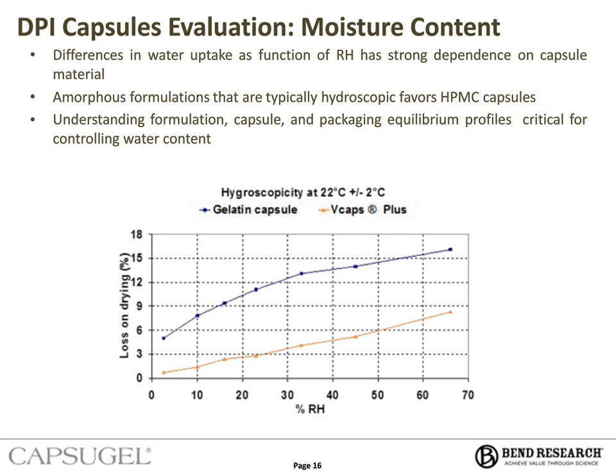And as you can see, a gelatin capsule equilibrated at 50% relative humidity, which is a standard, contains approximately 14% water. In comparison, an HPMC capsule contains less than 6%. So already you can see quite a difference. Both capsules being equilibrated with a water activity of 0.5.